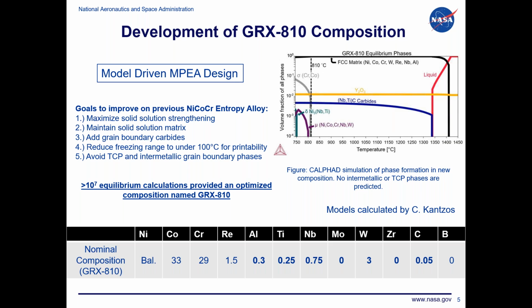And again, we want to avoid any other grain boundary phases that would be unstable, that would cause issues. And we wanted to maintain the printability of the nickel cobalt chrome system. So one way to do this is, if you at least reduce the freezing range, the temperature between the liquidus and solidus, you can expect that you have a better chance of having a printable alloy. So we set out these 5 goals.